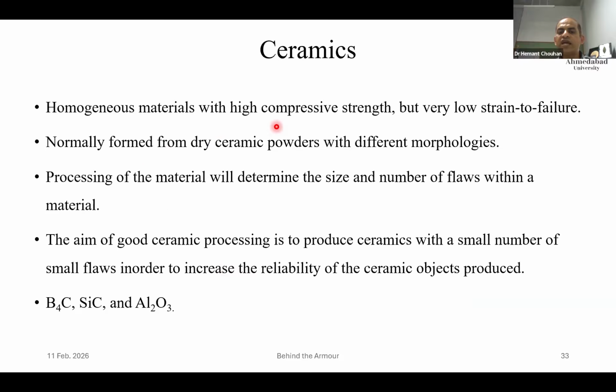So a homogeneous material with very high compressive strength but very low strain to failure is an option, and that is where ceramics come into the picture, because we are not interested in metal for the weight penalty reason. Normally we have ceramics in the form of powder, and then they are suitably processed to give us tiles. Now this can be a monolithic tile matching the dimension of your BP panel, or they could be in the form of multiple small mosaic tiles. They are to be placed on top. In my case, let's say there were 107 small tiles to be placed on a compression molded UHMWPE panel. The aim basically is to get good ceramic processing so that we can successfully defeat these 6 to 8 projectiles of high hardness.